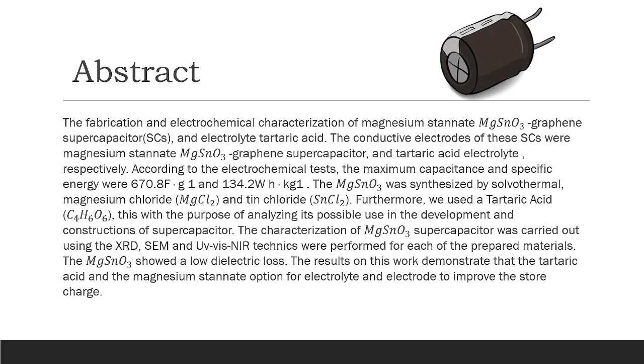Abstract. The fabrication and electrochemical characterization of a magnesium stannate graphene supercapacitor with a tartaric acid electrolyte. The conductive electrodes of this supercapacitor were magnesium stannate graphene and the tartaric acid electrolyte, respectively. According to electrochemical tests, the maximum capacitance and specific energy were 670.8 farad per gram and 134.2 watt-hour per kilogram. The magnesium stannate was synthesized by solvothermal method from magnesium chloride and tin chloride.